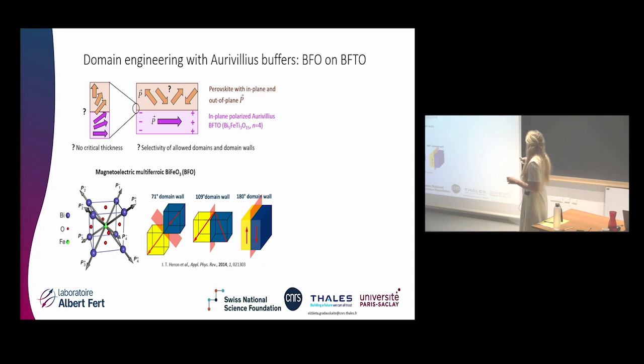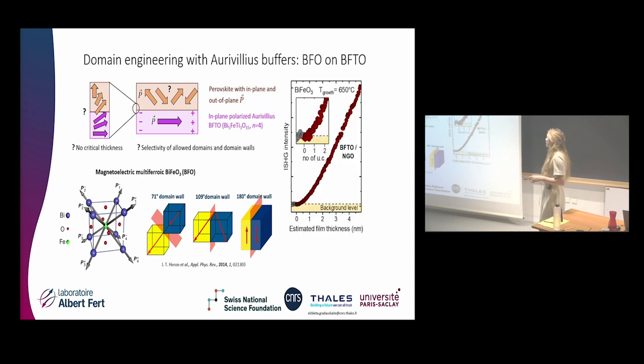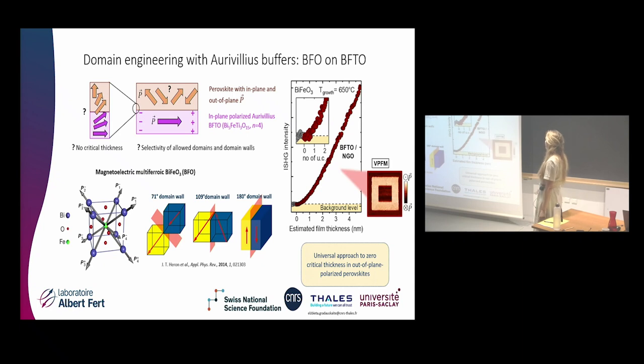And now we do the same SHG experiment, and once again, same result. We can see something already from the first unit cell. So it seems that this is a universal approach to zero critical thickness in such out-of-plane polarized perovskites. We can see that it's out-of-plane nicely polarized. We can reversibly switch it with an AFM tip. So all looks good. Now let's look into domains.